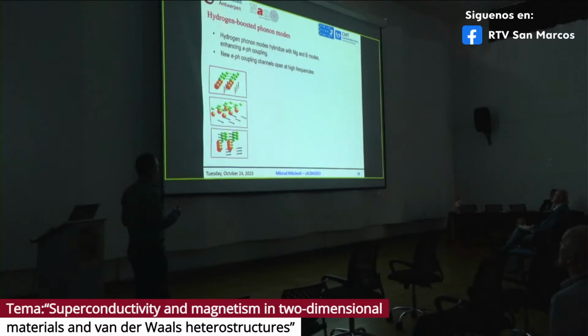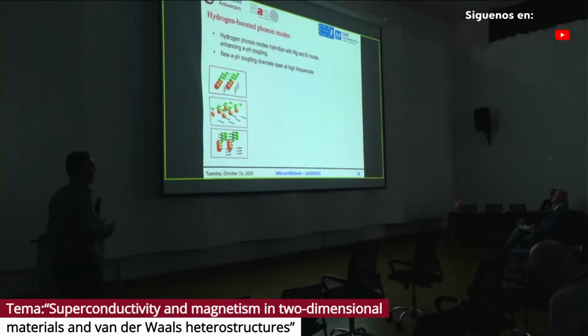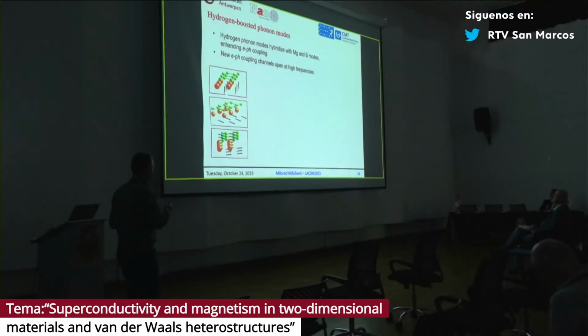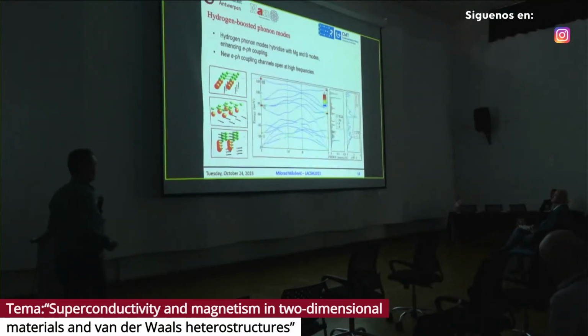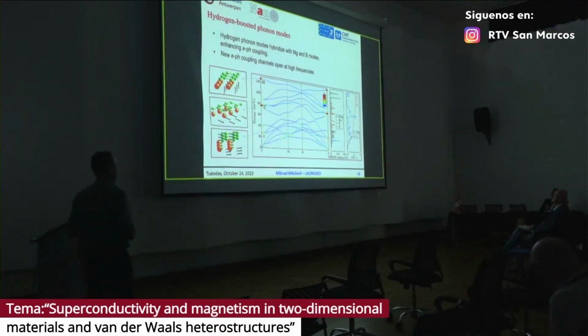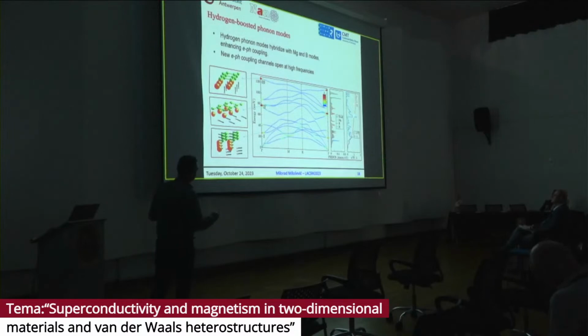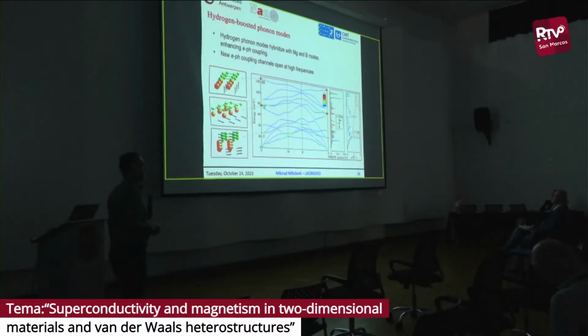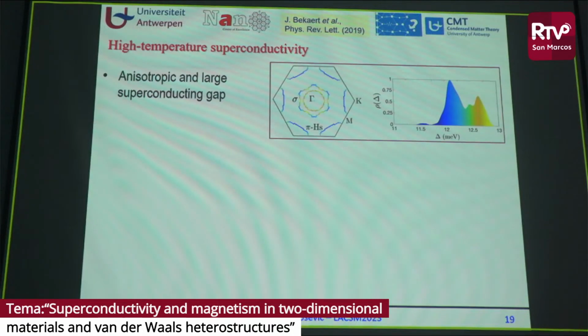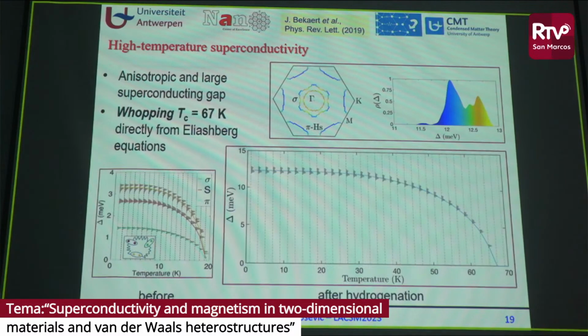But then we also have to remember that hydrogen is a light and mobile element. So because it's light and mobile, it mixes the phonon modes of the host material. So these three particular modes of hydrogen mix very well with the other phonon modes of this material. And as a consequence, we get electron-phonon coupling that by far exceeds the electron-phonon coupling of the original MgB2 monolayer. So instead of the three-gap superconductor that we had, now we have a single gap, anisotropic, but very high gap. You remember we had 5 to 7 meV, now we have 12 to 13 meV. And with strain, we can push this to nearly 70 Kelvin.